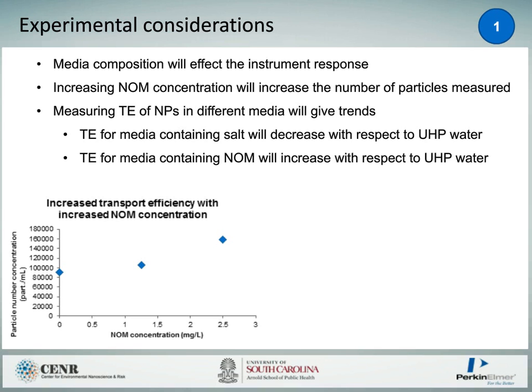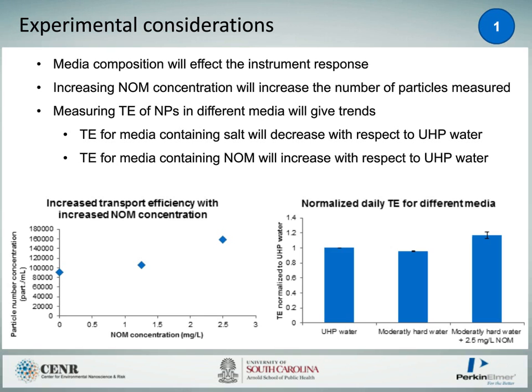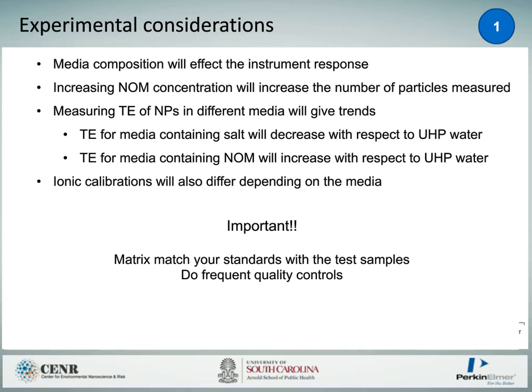So measuring the transport efficiency of nanoparticles in different media will give different trends. Transport efficiency for media containing salts will actually decrease. So if you look at the graph on the right-hand side, you have the ultra-high pure water, which comes out as a ratio of 1, because that's what we're normalizing to. And if you have moderately hard water that contains salts, we actually always get a slightly lower transport efficiency than you'd expect. And if you then add natural organic matter, we're getting a higher transport efficiency. So you have to make sure you matrix match your samples. The same will happen with your ionic calibration. So it's very important to matrix match your standards with the test samples and do frequent quality control to check that you still have the same amount of expected nanoparticles in standard solutions.